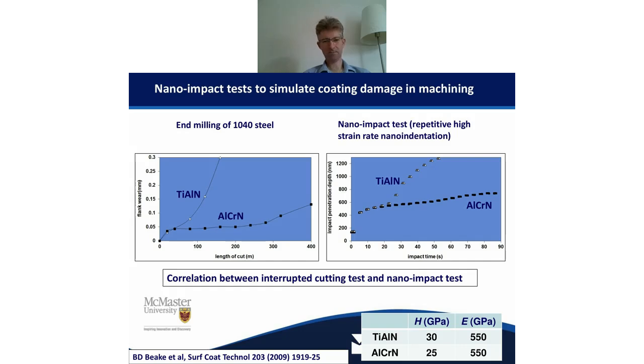But again, with these cutting tests, you had to stop and test these things each time, put them back in the same position, start again. So it's a very time-consuming test. And again, if we look on the right, we can see the impact test, and we can see in a minute and a half we get exactly the same trend, very consistent behavior. This just shows one test, but you can do it several times and get very consistent behavior.